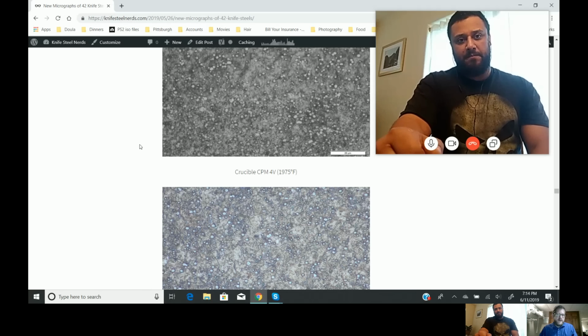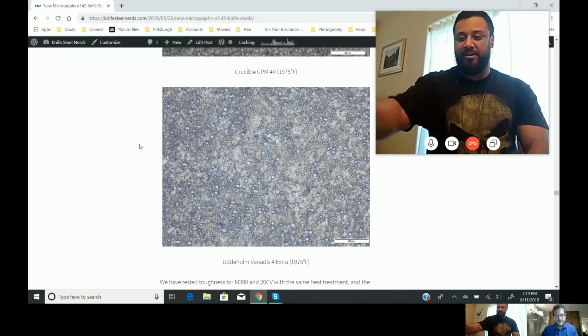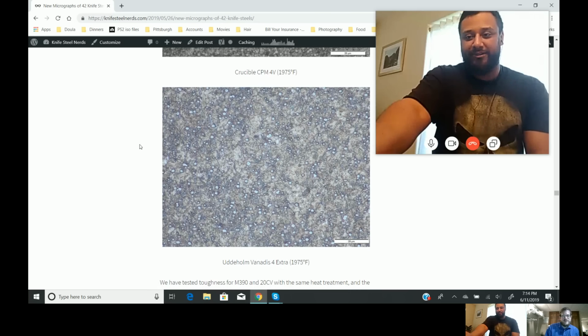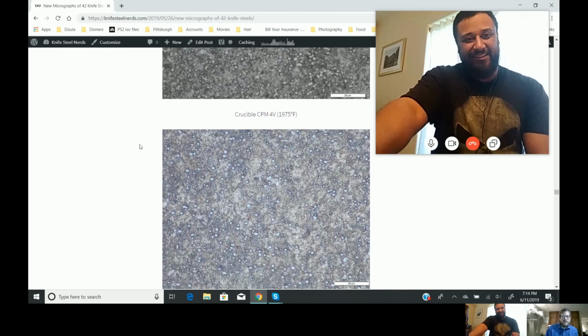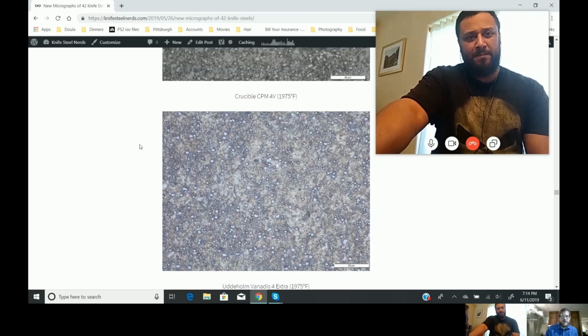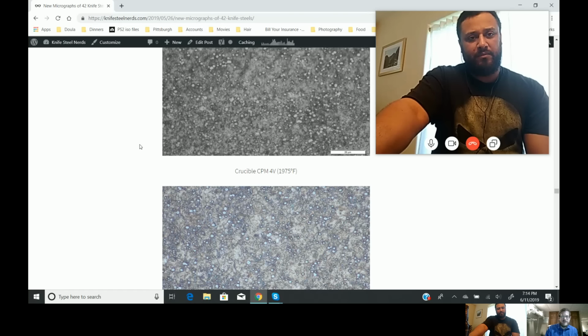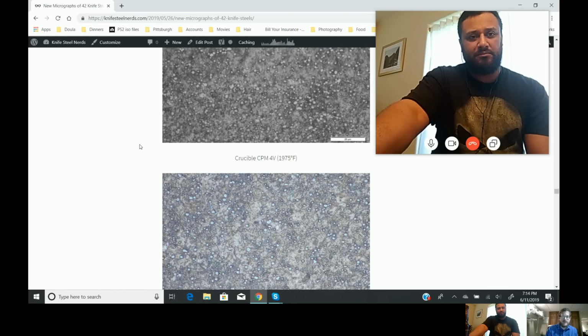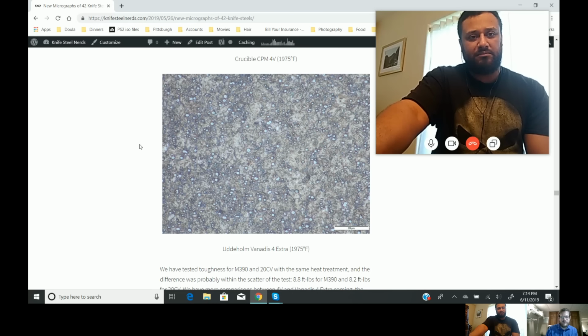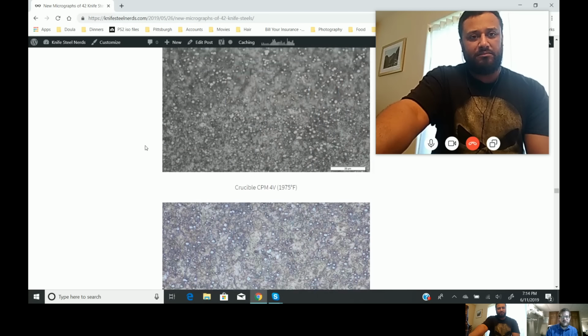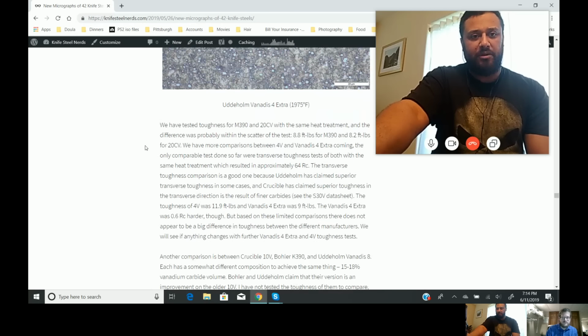Yeah, if the 4V is cheaper and easier to get, it's probably worth just using it instead. So yeah, you do pay a premium for the Vanadis 4 Extra import brew. And again, the toughness testing we've done so far, they're equivalent. The 4V was actually a little bit better in the test that we did, but we've only had one heat treatment condition that was identical between the two. So we need some more comparisons to really show if one is better than the other, but definitely not a 50% improvement by switching to Uddeholm Vanadis 4 Extra, because in fact the 4V was better so far. Interesting. We'll have to check that out some more.